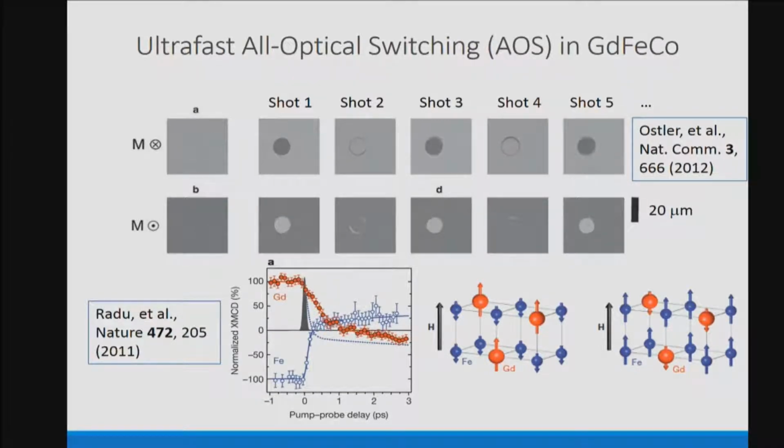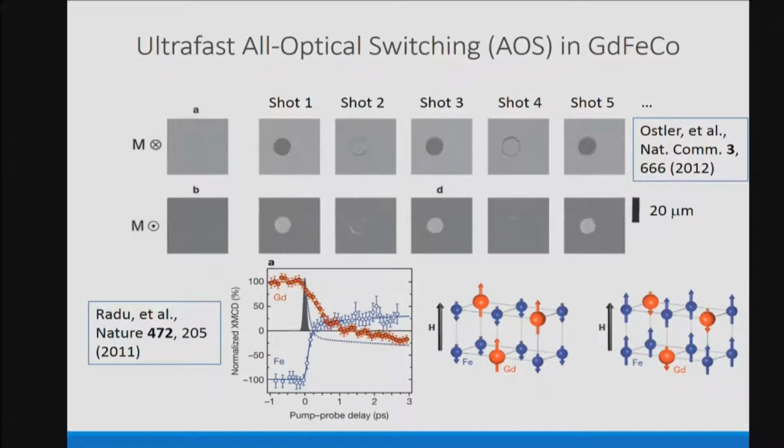And so that's the key thing that triggers this, the selective heating of the electrons, which requires very little energy because the heat capacity of the electrons is small compared to the heat capacity of the lattice. So you heat up the electrons to maybe 1,000 degrees, but by this time the lattice and the electrons equilibrate, and the net heating might be only 10, 20, or 30, maybe 50 degrees.